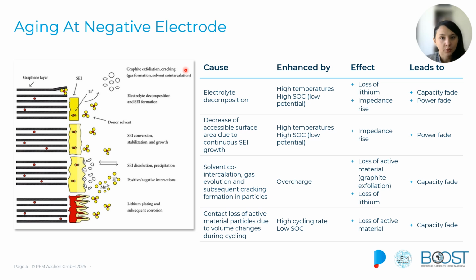At the negative electrode, or the anode of our battery, aging will cause mostly the formation and continuous growth of a solid electrolyte interface, that is this layer over here. This layer forms naturally as a protective barrier between the electrolyte and the anode materials, and over time it gets thicker and thicker and starts consuming the active lithium, and this will reduce the overall battery capacity. High temperatures and operating at high state of charge levels will accelerate the growth of this layer, also increasing the internal resistance of the battery and leading to the power fade.